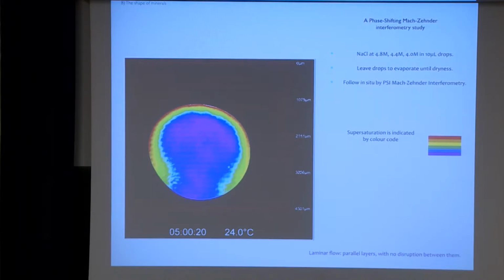Okay, so this is an interferometric study. It's a phase shifting Mach-Zehnder interferometric study. This is a crystallizing drop. Okay, so you will see here now a crystal of sodium chloride, which is cubic, so the crystal should be a cube, right? And then you see that the supersaturation is higher. This is the color code. This is higher at the edge of the evaporating drop. Okay, and because the drop is that way, we have a gravity effect.